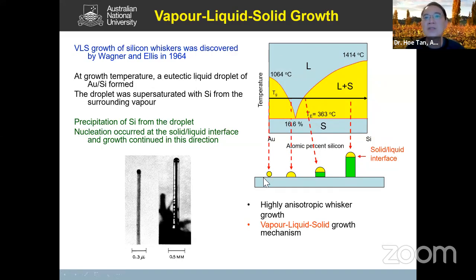So the way this works is they have a silicon wafer and then they put a gold particle on it. At the time they are not talking about nano. You can see the scale here, they are microns or even millimeter scale. So they have a silicon wafer and a gold particle, they heat this up and pass silicon vapor in the form of silane.